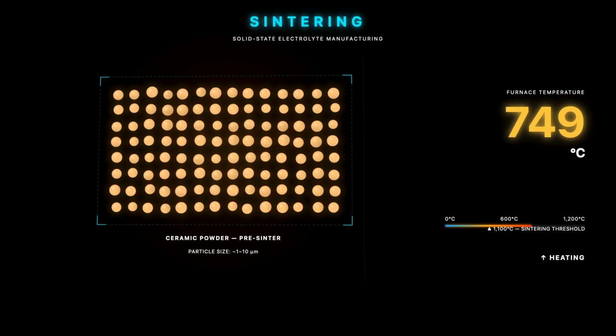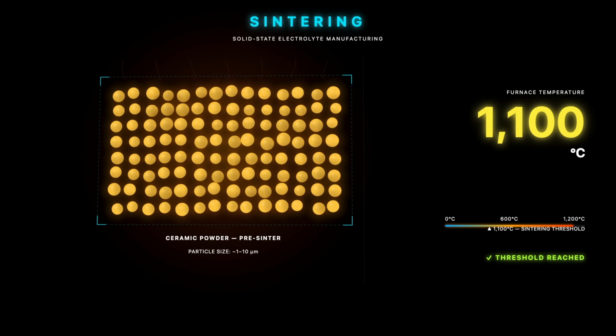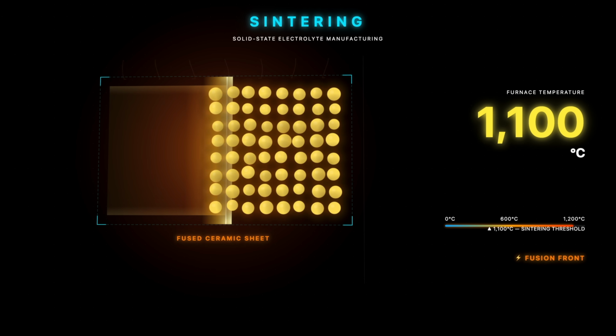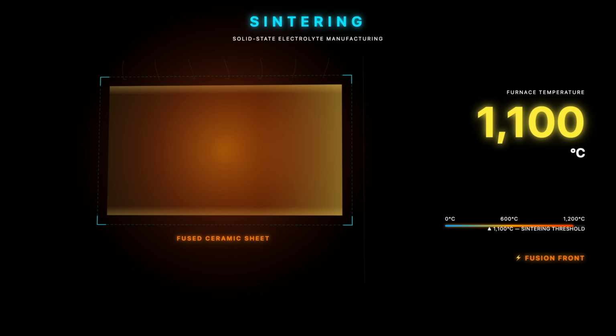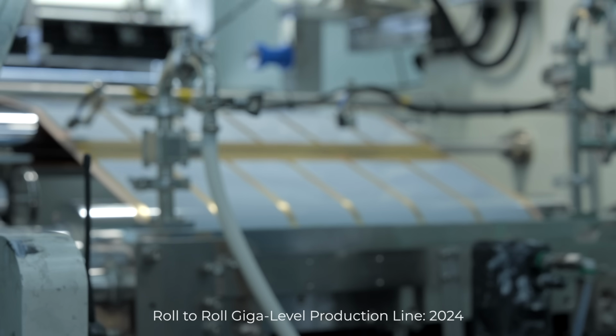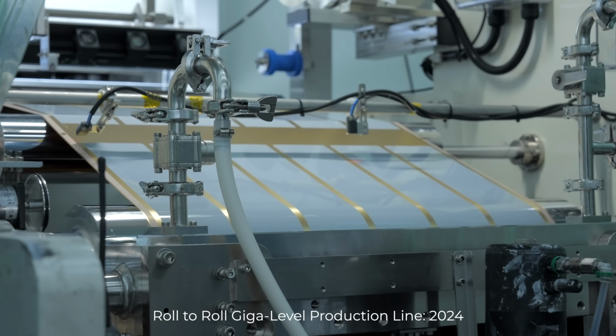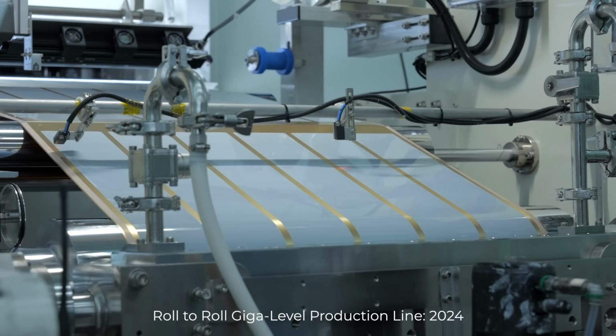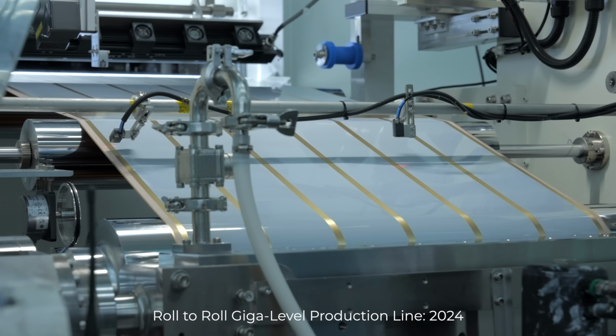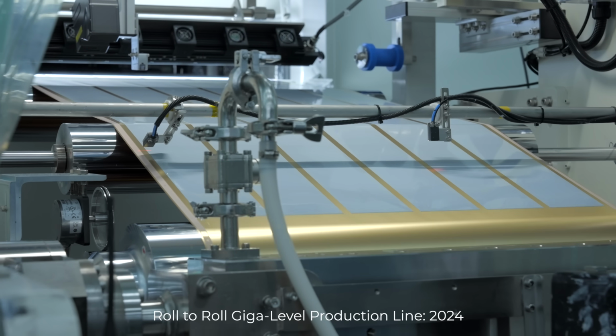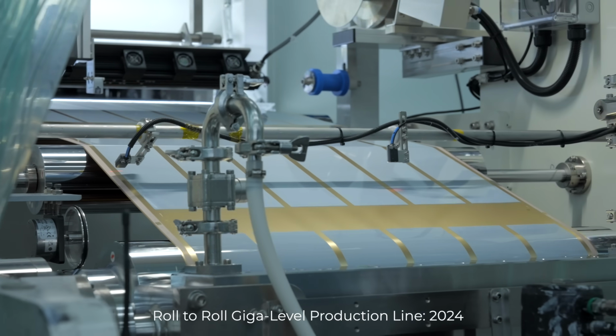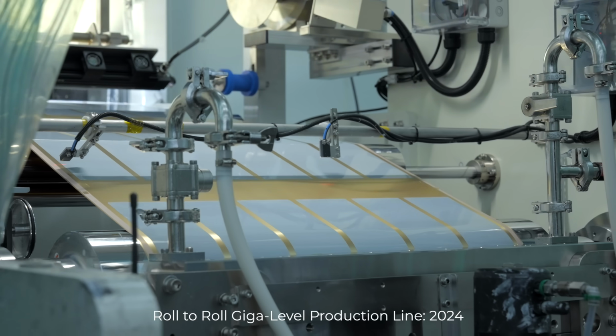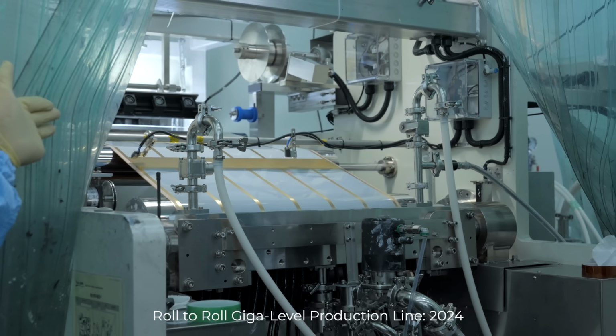You heat ceramic powder to over 1100 degrees Celsius until the particles fuse into a sheet. It's slow, it's offline, and it poses a major limiting factor in the manufacturability of solid-state batteries. ProLogium chose differently from day one. Their ceramic separator is made by a wet film coating, the same process used for cathode and anode coating in any conventional battery factory. You mix the ceramic into a slurry, you coat it onto a moving roll of metal